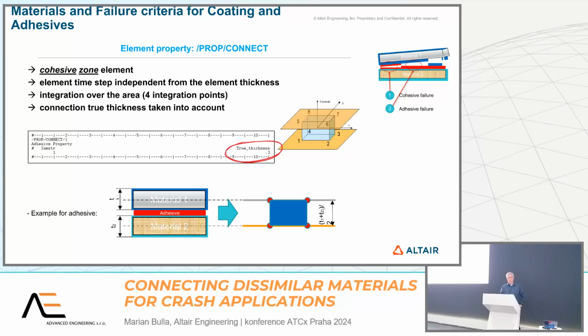First of all, modeling with cohesive zone elements. The adhesive layer can be very, very thin and small. You can now also model it with a height, whatever you want, and apply a value for the true thickness. Why? Because you model this adhesive with a solid element, but it is not a continuum mechanical solid element. It's a trick. It's just a cohesive zone element, which can have a volume of 0. No issues. It has only 4 integration points in the mid-plane, which act like 4 springs. So a very simple approach, which exists in any solver, in Altair, in PAM-CRASH, Abaqus, Radioss, of course.